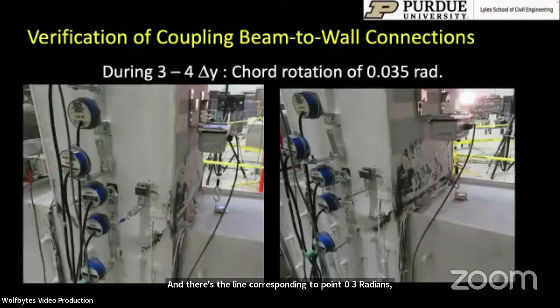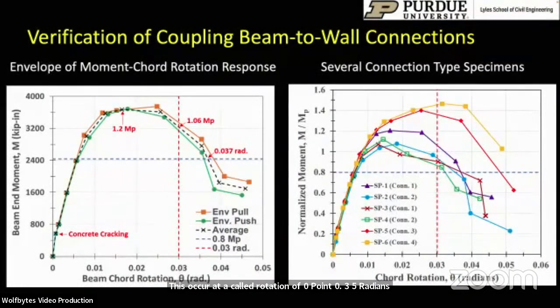So we took these experimental results, and I'm showing you here a couple of photographs. You can see the formation of local buckling in the flanges of the coupling beams. You can also see the occurrence of fracture right there in the flanges and portions of the web as well. This occurs at a chord rotation of 0.035 radians. We took the envelopes of the moment rotation responses and we plotted them so that we could look at what was the rotation capacity of the connection. For example, this connection had a rotation capacity of 0.037 radians, which corresponds to the reduction in the moment capacity of about 80% of Mp.